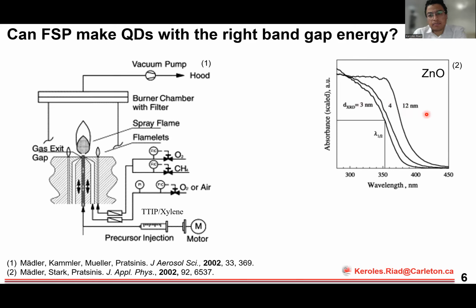And as you see, as the crystal size decreases, the wavelength shifts to lower values, a blue shift, and that means higher band gap energy. And the way Professor Madler pushes the crystal size to the extremely small sizes you see here is by adding silica.